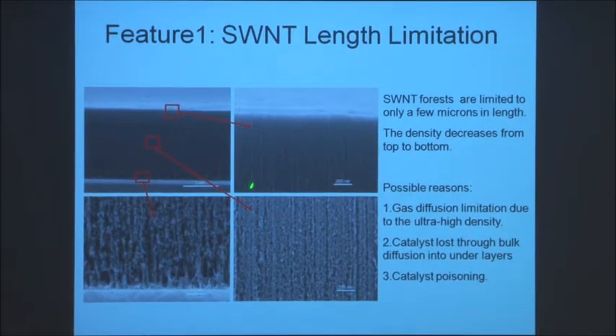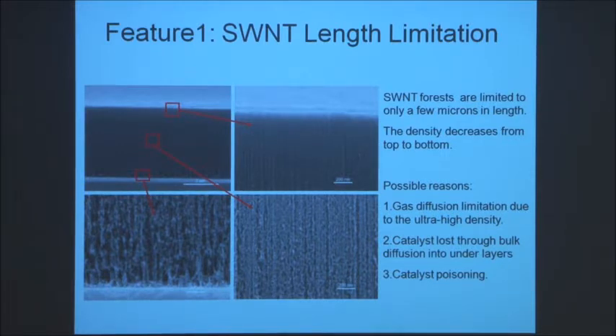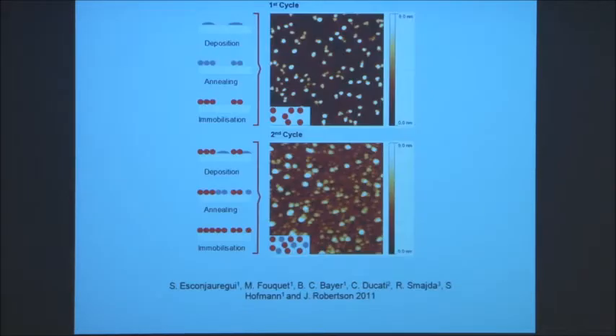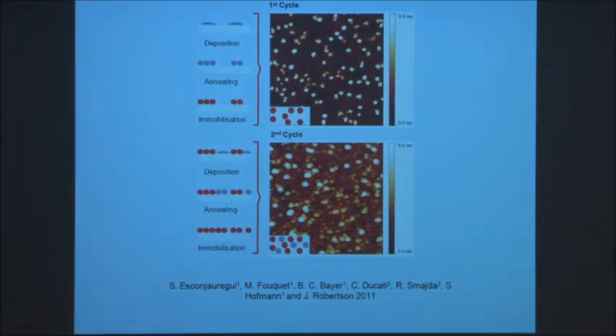So they're essentially limited by how close you can get the catalyst together. And you might think it's simple. All you do is you put down some catalysts, easy, and then you put down another bunch of catalysts, and that gives you more and more bunch. But what happens if you put more catalysts on this catalyst? All that happens is these catalysts grow bigger.